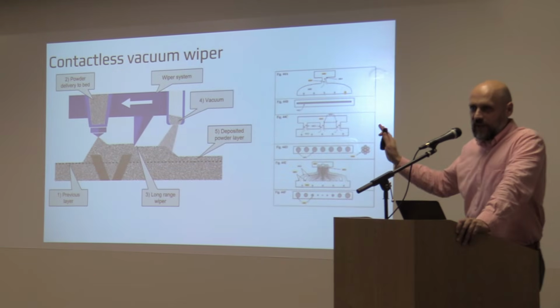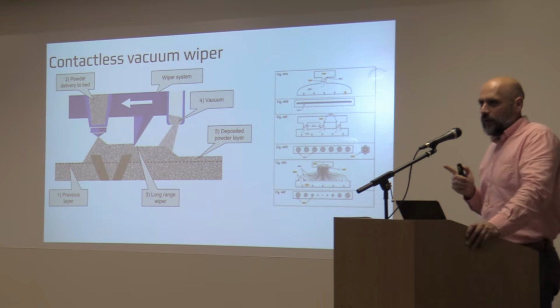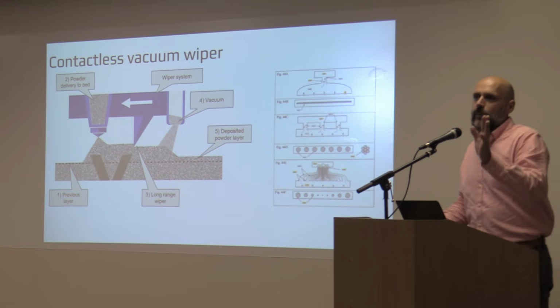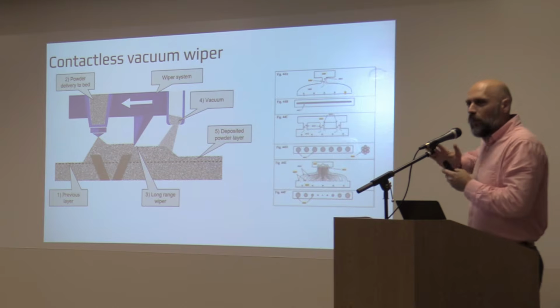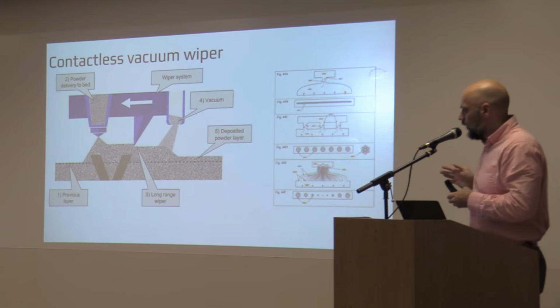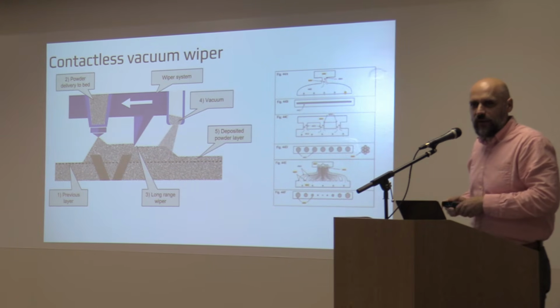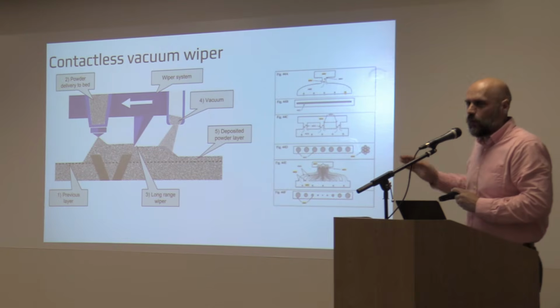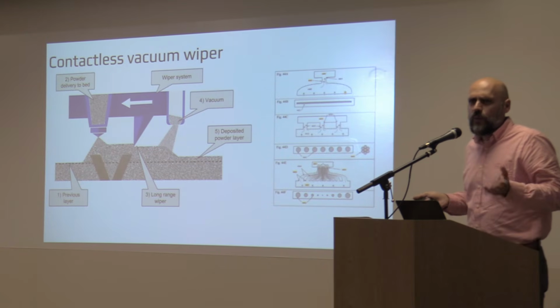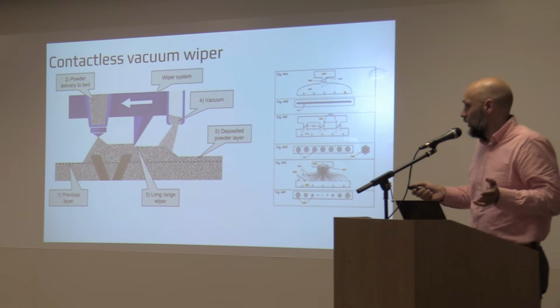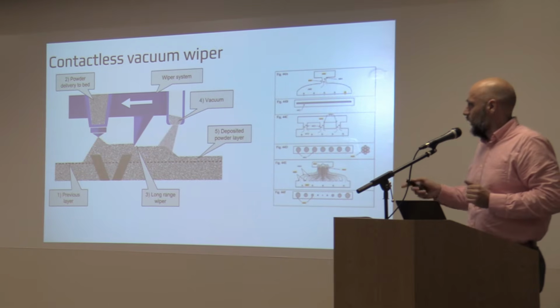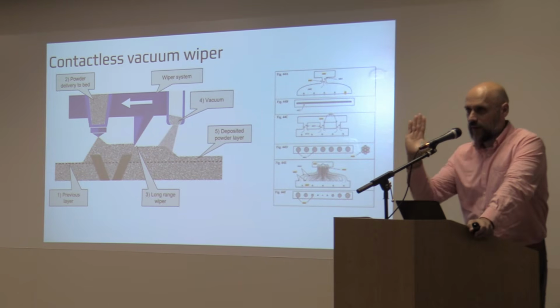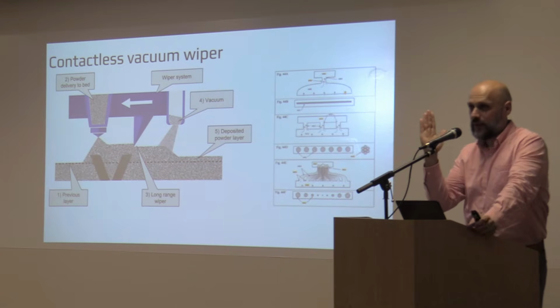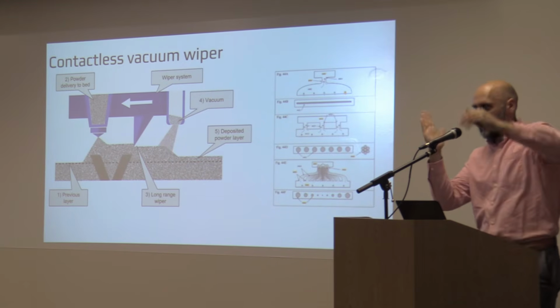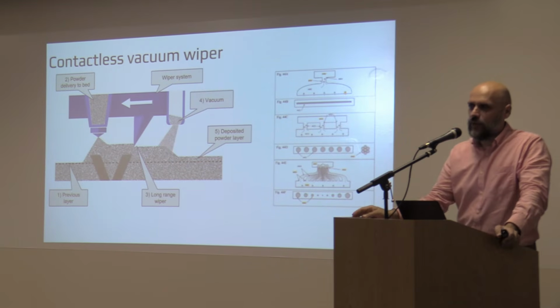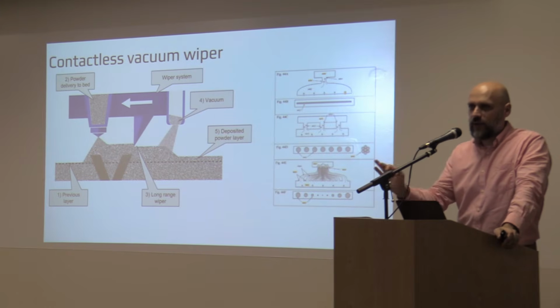So first, let's talk about the contactless vacuum wiper. This is important because you want to have no supports. You're pushing metal powder over your part that's floating. Well, this powder has the consistency of water when you push it. You're going to move the part, and then you lose it. You don't know where it was. So it's important to not touch it. Also, when you have something going vertical without supports and you keep pushing it, it keeps bending and bending. Also destructive. So it's very important to not touch the part.